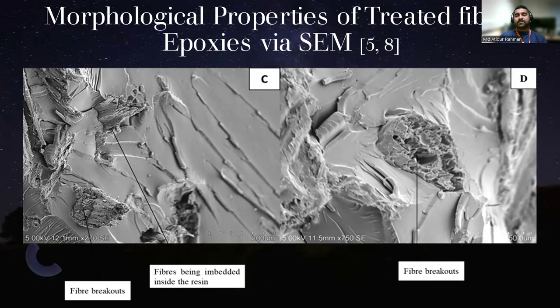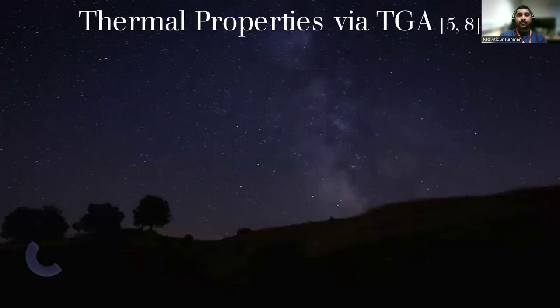And that is because we have seen earlier, when we did this AFM on the treated fiber, the surface becoming rougher, and even the hemicellulose has been taken away. A rougher surface is good for absorbing more resin, and all the porosity is filled with the resin. That's why over here we can get high thermal and mechanical properties because of the good adhesion surface. Let's see the thermal properties via TGA.